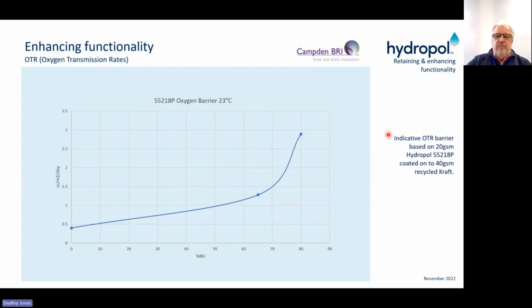In terms of oxygen barrier, obviously oxygen depends on the different RH. As we relate to paper, we look at the 70 percentile because beyond that, paper swells. So realistically, we're looking at around about 1.5. If we're talking tropical, it's 3. Around about 50, it's 1. So it's a good OTR barrier in itself inherently.